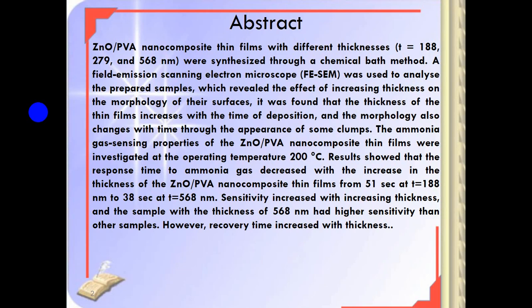The ammonia gas sensing properties of ZnO-PVA nanocomposite thin film were investigated at an operating temperature of 200 centigrade. Results show that the response time to ammonia gas decreased with the increase in the thickness of the ZnO-PVA nanocomposite thin film, from 51 seconds at 188 nanometers to 38 seconds at 568 nanometers. Sensitivity increased with increased thickness, and the sample with the thickness 568 nanometers had higher sensitivity than the other samples. However, recovery time increased with thickness.